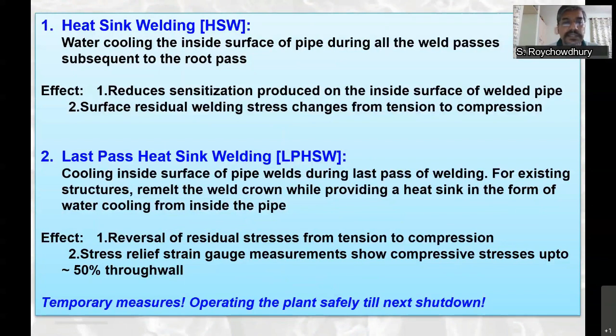Also, in last pass heat sink welding, you pass this cold water in the last pass of the welding. What it does is that it will revert the residual tensile stresses to compressive stresses on the ID side. That will again help in preventing SCC. But these are of course temporary measures, to operate the plant safely till your next shutdown.